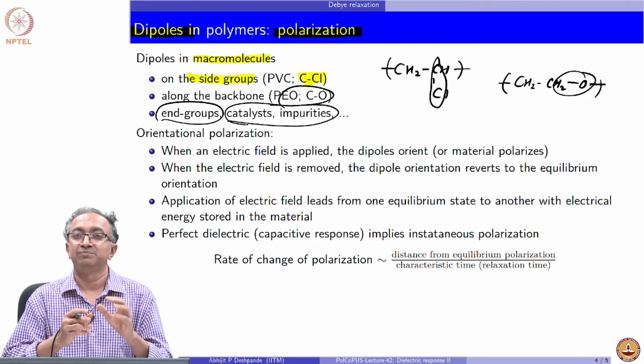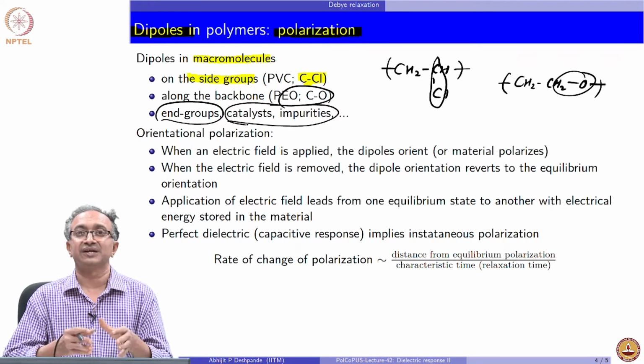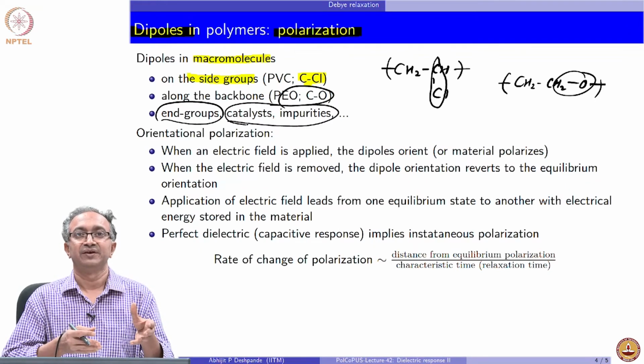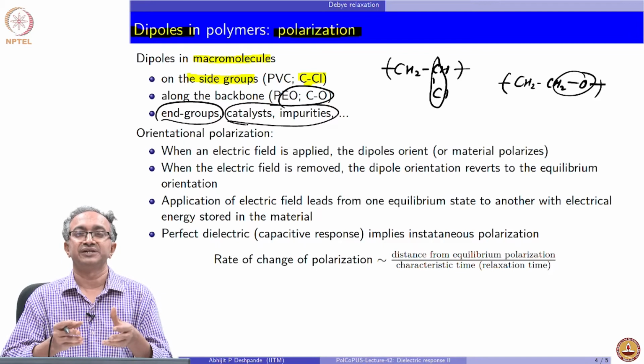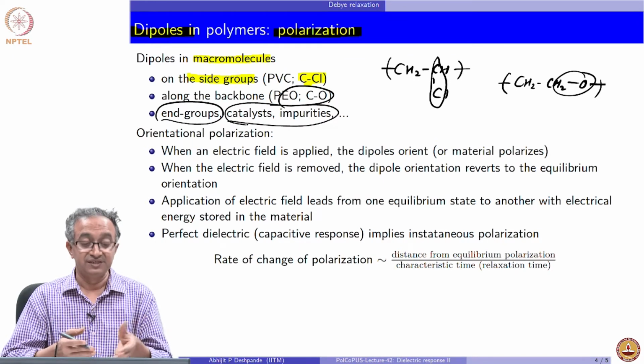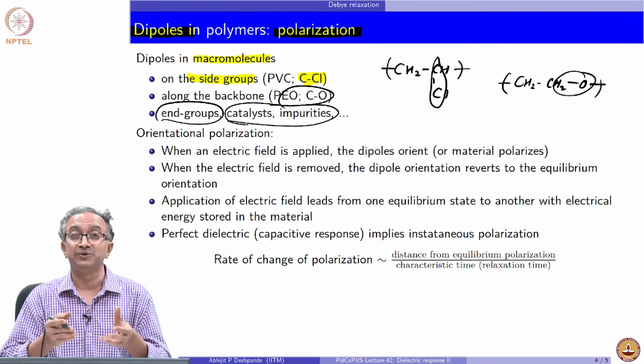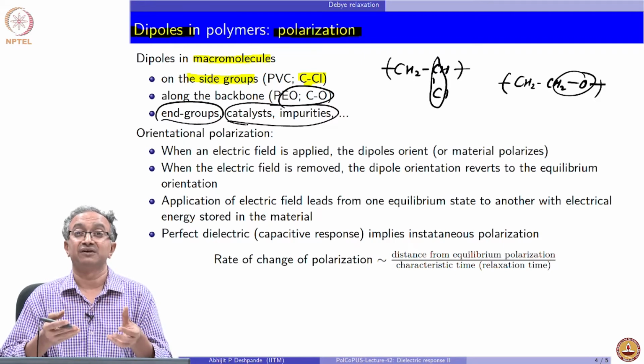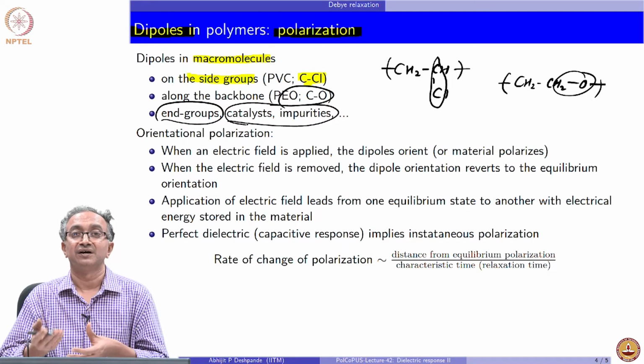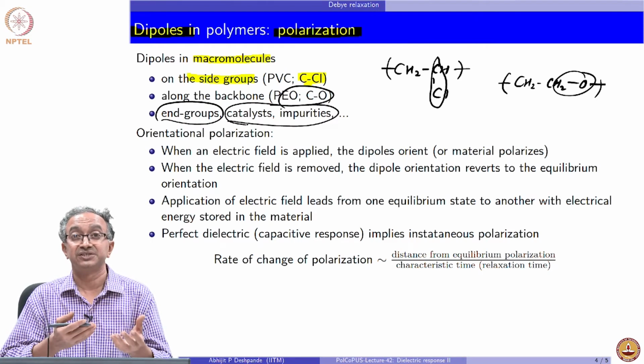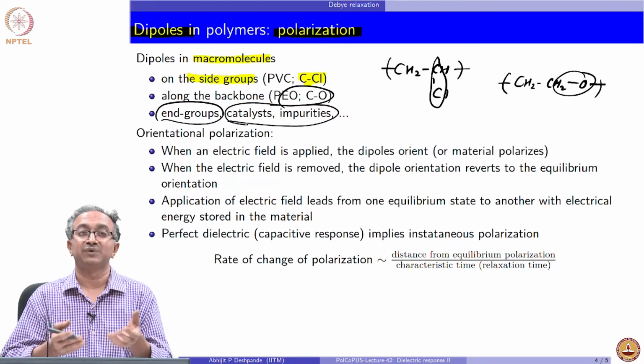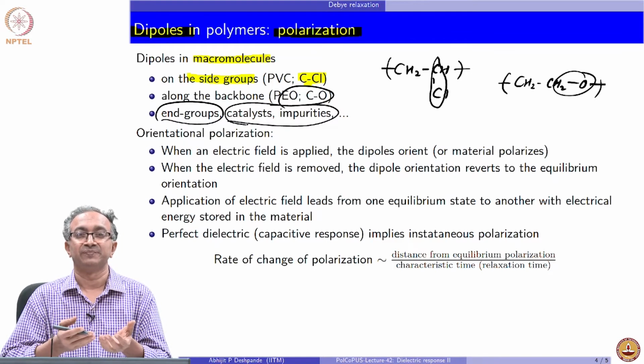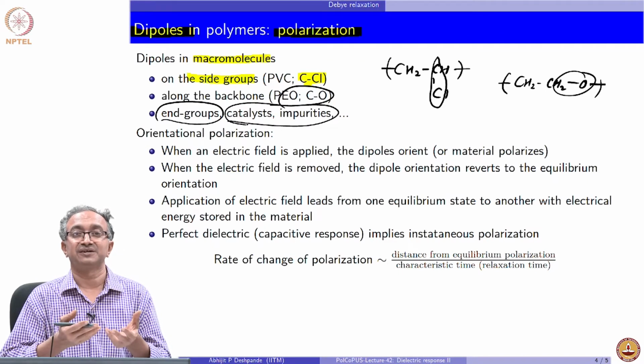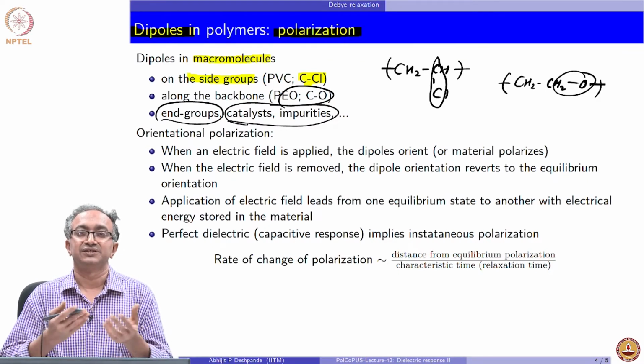But mind you, the impurities present and their analysis can also tell us about macromolecular flexibility. For example, if there are these catalyst particles and impurities and they are not able to move, that implies that free volume in the polymer is less. So, therefore, it may be in the glassy state. But if these catalyst and ions and impurities can move about, then it may be that there is molecular flexibility in the system and the material has gone to a rubbery state. So, glass to rubber transition in a macromolecular system could be looked at by looking at the migration of these impurities, which is again a dissipative phenomenon associated with motion of these charged entities.